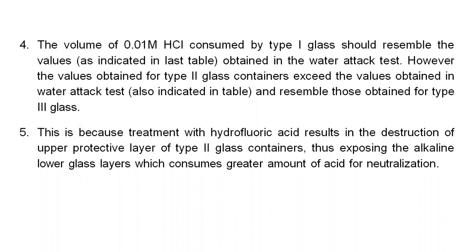test. However, the values obtained for type 2 glass containers exceed the values obtained in the water attack test, also indicated in the table, and resemble those obtained for type 3 glass. This is because treatment with hydrofluoric acid results in the destruction of the upper protective layer of type 2 glass containers, thus exposing the alkaline lower glass layers, which consume a greater amount of acid for neutralization.